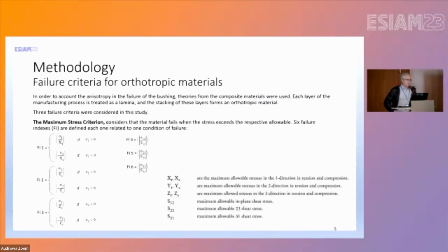In order to account for the anisotropy in the failure of the bushing, theories from composite materials were used. Each layer of the manufacturing process is treated as a lamina, and the stacking of these layers forms an orthotropic material. Three criteria were considered in the study.